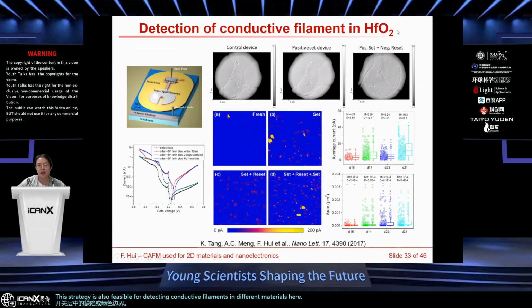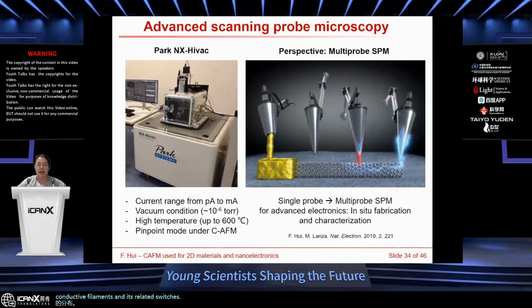For example, we also repeated the experiment in hafnium dioxide. We have seen the changes of the conductive filaments under different states, for example, the fresh state, the set state and the reset state. And we statistically analyze the data set. In this case, we can conclude the distribution of the conductive filaments and its related switching mechanism.